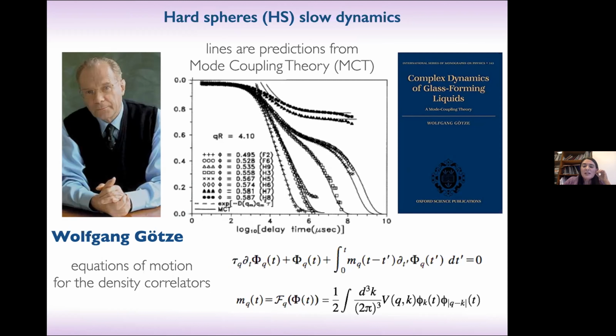The important thing is that mode coupling theory qualitatively reproduces the features, because you can see that the theory really reproduces the data well, except for the fact that the theory predicts the onset of the transition at a much smaller packing fraction, 0.52. But for our purpose today, this is quite irrelevant, because the important thing, and how Van Meegen plotted the data, and how we will do it also later, is that you need a mapping. You need to know where your experimental or numerical glass transition is. You shift the mode coupling theory predictions to the expected critical volume fraction, in this case, or temperature for glass formers, and then you can reproduce the behavior of the density correlators around this transition.